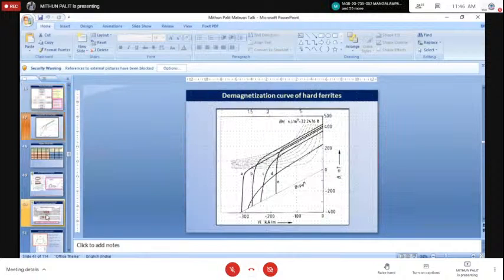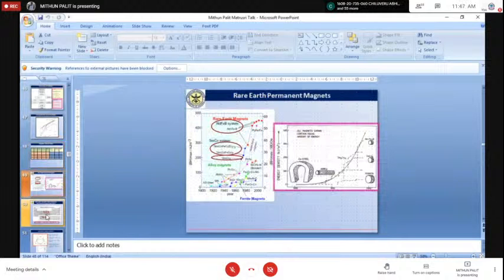You can see this demagnetization curve, and when you compare it with the alnico, you see there is a substantial improvement of the remanence as well as coercivity, and accordingly the energy product is also high. There are different grades of hard ferrites. They have Br in the range of up to 4000 Gauss, coercivity in the range of 2.5 to 3.5 kilo-oersted, and energy product of 3.5 to 4. These magnets can be operated up to a temperature of 300 degrees C.